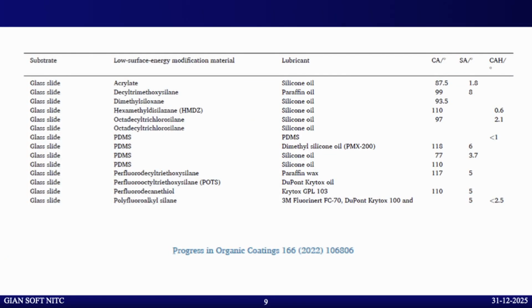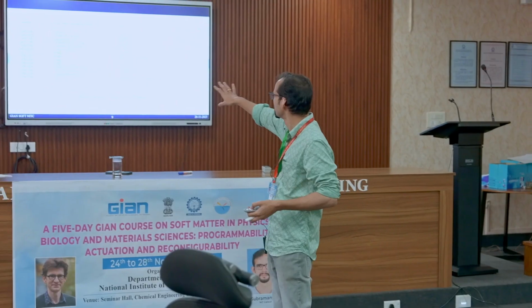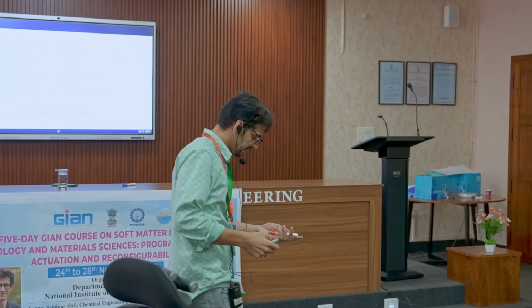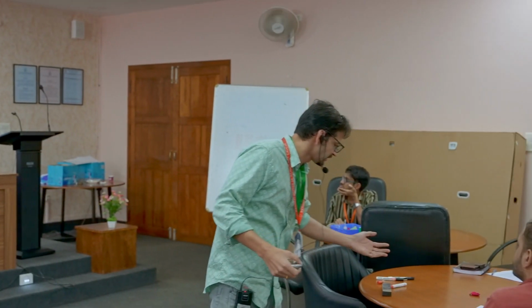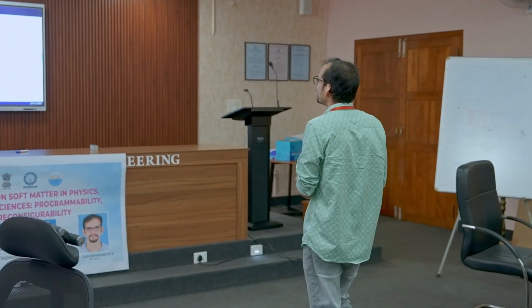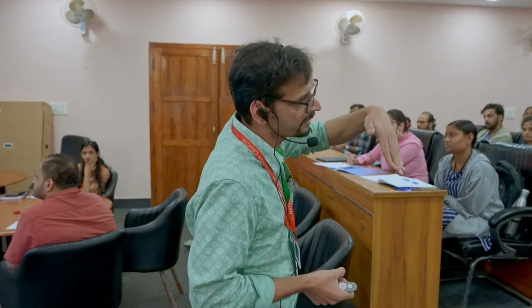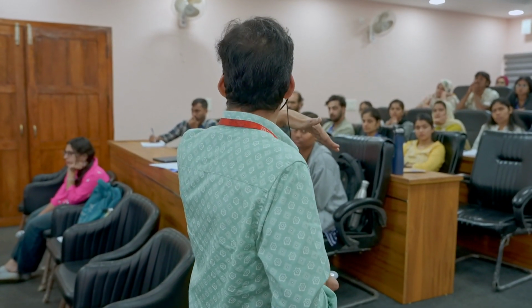Okay, so this is for giving you slides, like, in that reference, you can see different combinations. And you can see a striking difference now. In the previous classes, we were discussing hydrophobicity, sliding angle, contact angle, and all, right? You see here, the contact angle is typically around 100, 120 only, right? It is not about 160, 170. What's the point? And the sliding angle tells you at what angle the droplet starts to slide. You can see it's very small numbers, right? In some cases 8, otherwise it is 2, 3, 4, this kind of thing, right? It tells you that even though there is an oil layer present, with slight tilting it slides, but in the case of a normal solid surface, it will not happen, right?